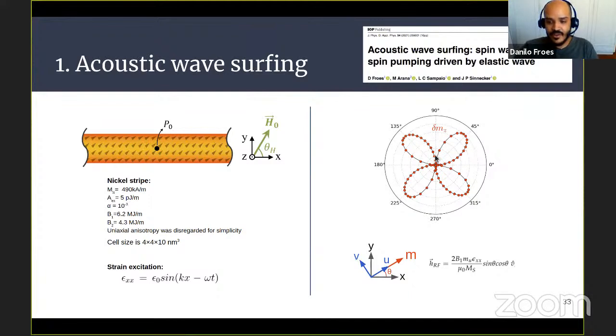We get a very low amplitude. When we are at 45 degrees, we have a maximum. Maximum amplitude spin wave formed there. And this can be explained by the magnetoelastic effective field, okay? So I'm going to show it briefly.